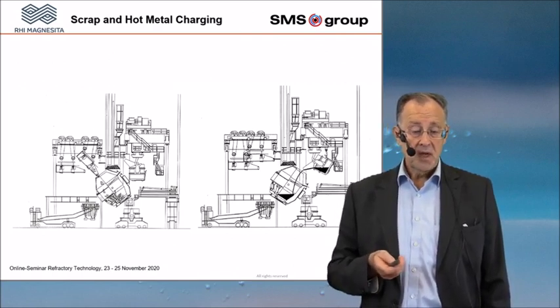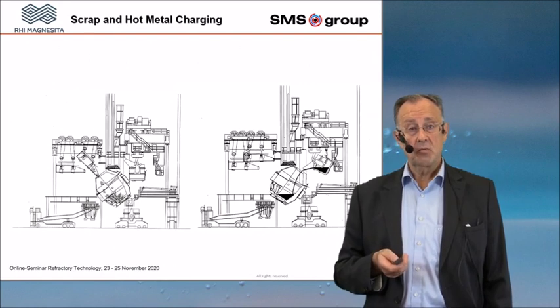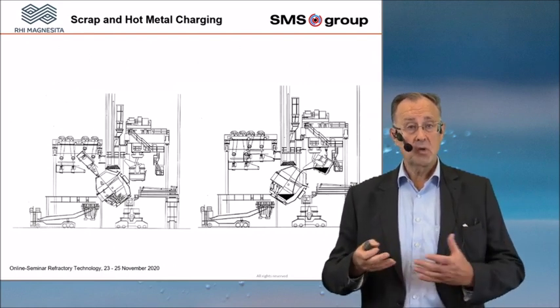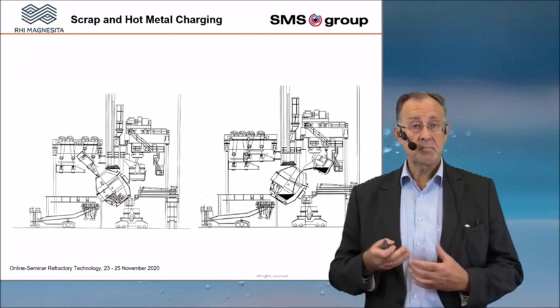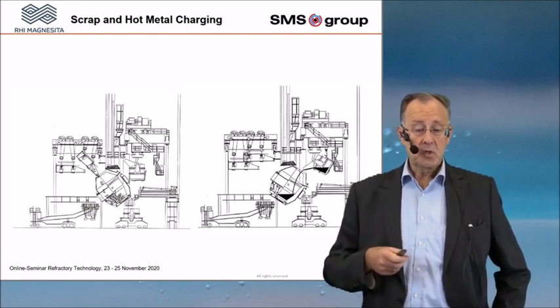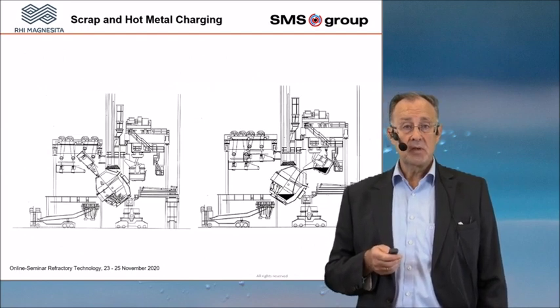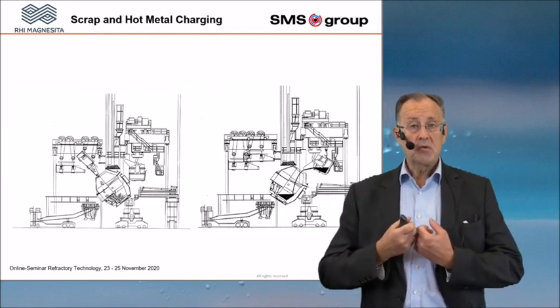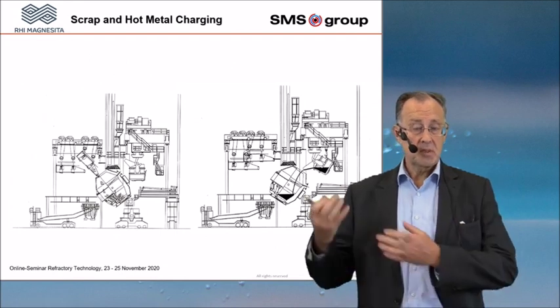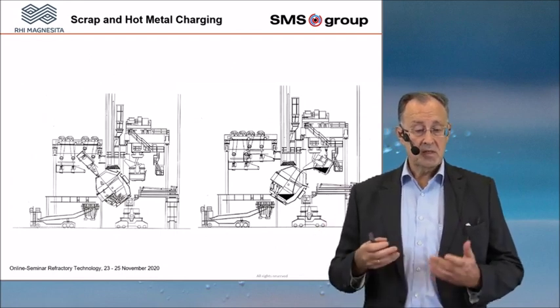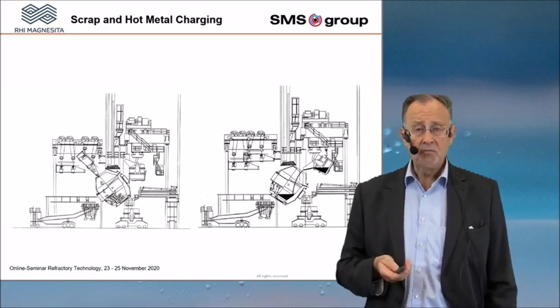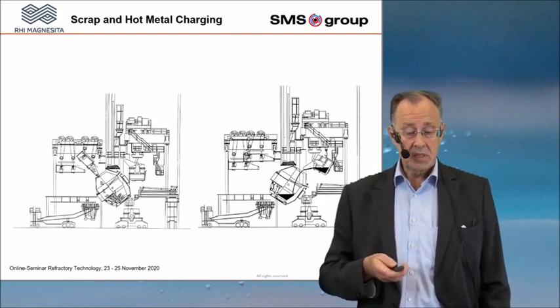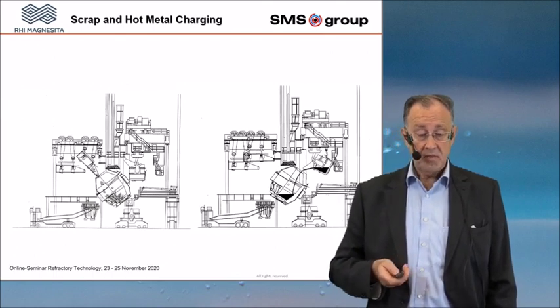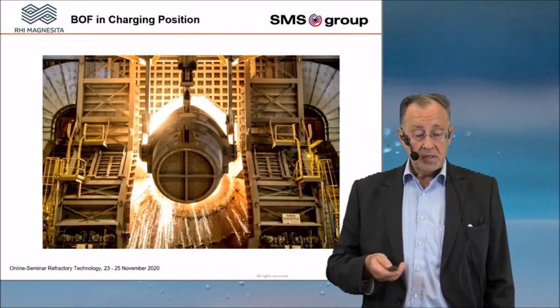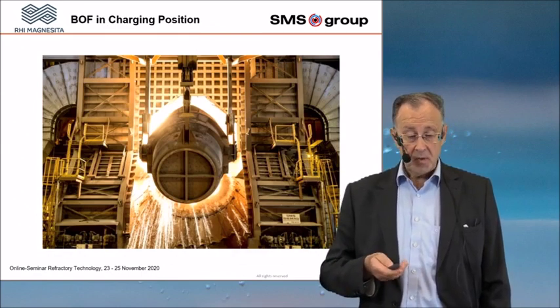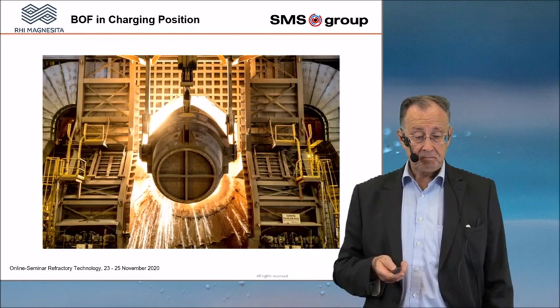This is important because at first you have to charge the scrap inside the converter, because very often, especially in winter time, you have some humidity, some water in the scrap, some ice or snow. And if you would do it in the opposite way, then the risk is very high that you get an explosive evaporation of water, and the scrap is thrown out of the converter, and it is from the safety side really critical. So that means at first you add scrap, and later on then hot metal. Here is a picture of a converter where the hot metal is filled in.